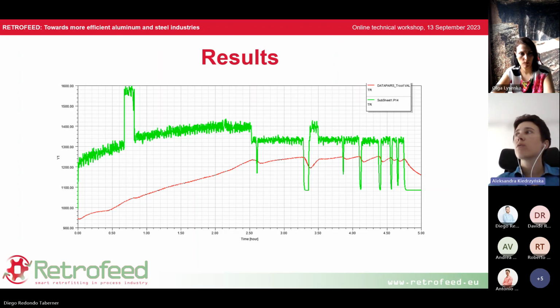Here we can see the comparison between the measured value, the red line, and the simulated, green line. As we can see, the discrepancies are visible. However, the roof sensor, which is simulated here, is shielded and indicates the temperature changes with a considerable time lag. We can also see here the step change of temperature caused by sudden release of volatile organic compounds and their combustion with added oxygen. Next slide, please.